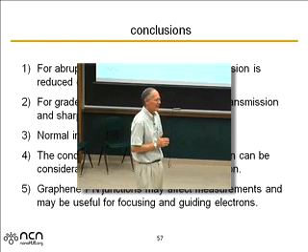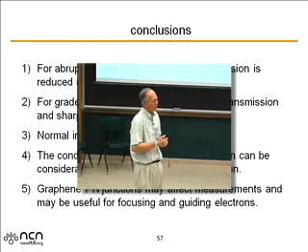They tunnel a very small way into a semiconductor because the band gap is very big. In graphene, when you put a metal down on graphene, there is no band gap. So these metal states can tunnel in, and you can get these metal-induced gap states which affect the electronic structure, and which it seems under some conditions can be quite important. So there's a lot of things that need to be thought through carefully here about exactly what these metal to graphene contacts do. And I don't think it's fully resolved yet.